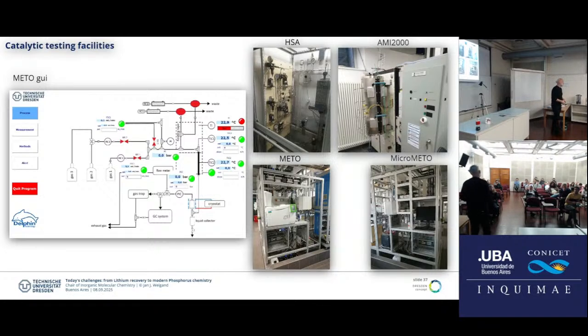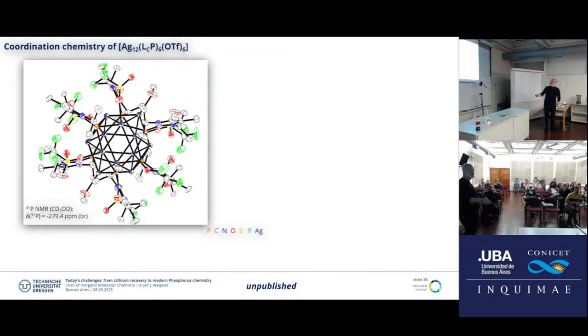ethylene oxidation to ethylene oxide, for example, is done on a silver catalyst. And if you can drop the temperature by 100 degrees, the process would be much, much more sustainable. And those clusters actually offer something like this. Because if you look also at the structure itself, I told you that the remaining triflate coordinates to 6 silver atoms. So we have silver atoms which are not coordinated.